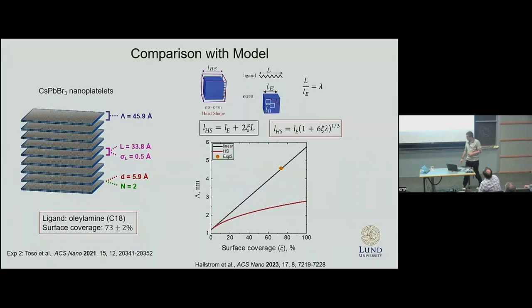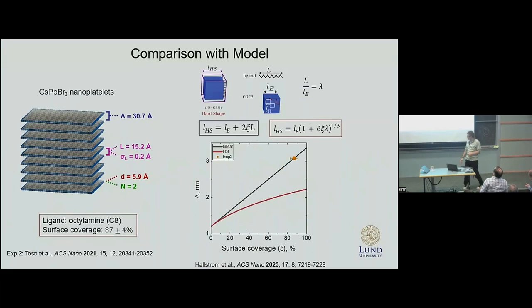For example, for the case of platelets, however, we knew the surface coverage quite well, and we knew the ligand, and it lands us exactly on this black line, which is the case for two hard surfaces, where the surface length is much larger than the ligand length. You might say this is just one data point for oleylamine, but we also had data for octylamine, C8, and also knew its surface coverage, and again we landed right exactly on this line.